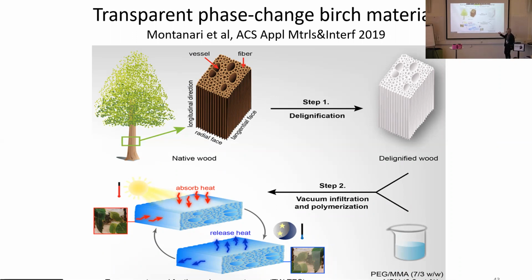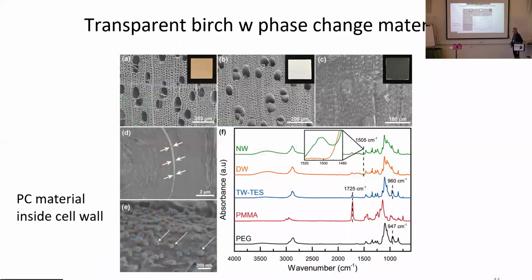So in other words, your transparent wood panel will be able to absorb heat when it gets too hot and release heat when the temperature goes down. And the key is really to get the phase change material inside the cell wall. And I think this is the essence, that we are trying to do difficult things to control the distribution of our active additives. And I think this will provide us with new opportunities also in the future.